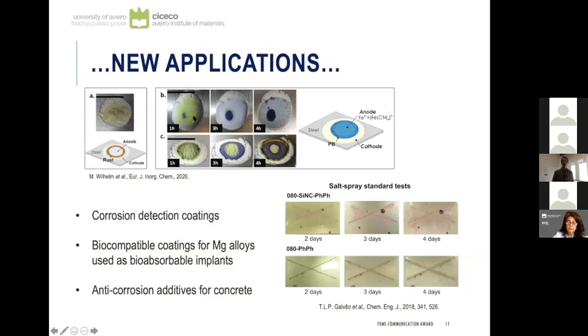And actually, we developed additives that could signal the occurrence of corrosion. We see here one example, which is using additives with hexacyanoferrate, and hexacyanoferrate reacting with oxidized iron, giving the Prussian blue. Other situations here use pH indicators, so we can see here that the encapsulated phenolphthalein can change color when we have corrosion, whereas when we have the phenolphthalein just added to the coating it doesn't work, it's deactivated.